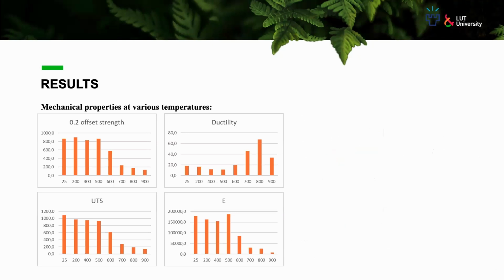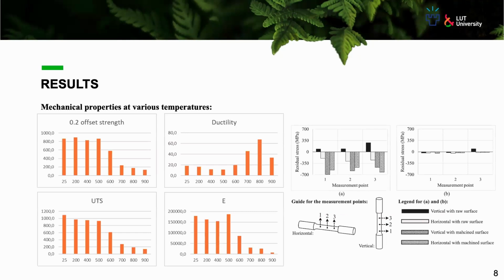But in the heat-treated version, before going to that, we can also consider the effect of residual stress after 3D printing, based on our previous results. The samples after 3D printing show a significant amount of residual stress. The samples used for high temperature tensile tests were built in the horizontal direction. So if they are exposed to heat, these compressive residual stress values can go to 0. So it can also have an influence on these results here.